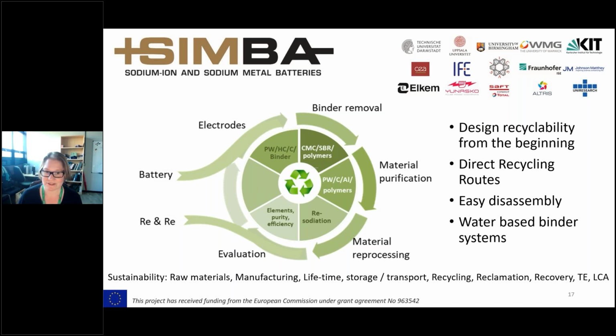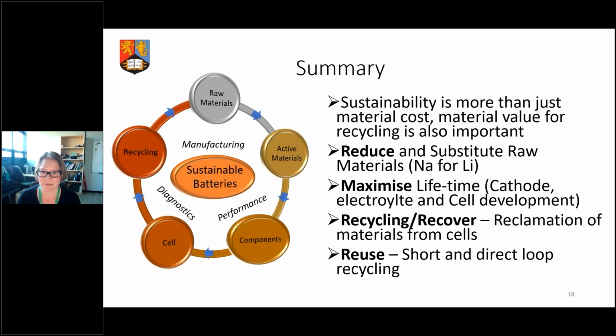What we can also do is start to design in ways for recyclability, so design for disassembly, such that we can use water-based binder systems, remove some of the glues from the battery pack so that we can reclaim these materials much more easily and with less energy inputs. So making it a more viable process. And certainly for sodium ion, I think this is what we need to do.